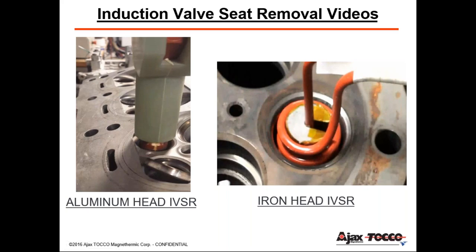In a matter of seconds, that valve seat was heated from room temperature to about 1,400 to 1,500 degrees Fahrenheit, while the cylinder head itself remained cool — we are focusing the heat only in that seat. Because of that, the seat is constrained by the cold head and forced to grow along its length, and when it cools it's been plastically deformed, allowing removal with minimal force. That entire process from heating to cooling to extraction takes about 30 seconds, where a lot of the cost savings come from core retention, labor reductions, and safety.